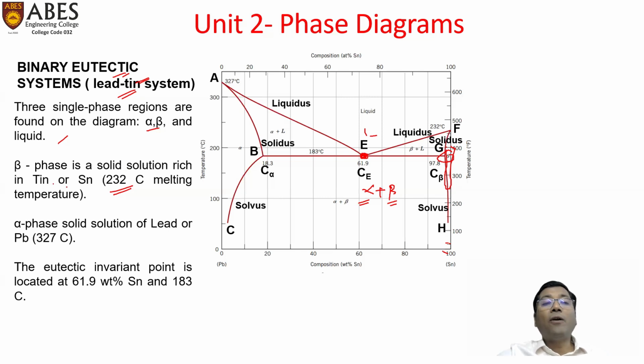Solid solution rich in tin, or Sn, having 232 degrees. 100% tin has 232 degrees Celsius as the melting point. Here it is marked. Alpha phase is a solid solution of lead, with 327 degrees centigrade. This complete region is alpha phase, where entirely alpha would be present, an entire single solid, and there would be 100% solubility of tin in lead, because here lead is 100% and tin would be 0%. So at this 100 and 0 combination, the melting point of lead is 327 degrees Celsius.